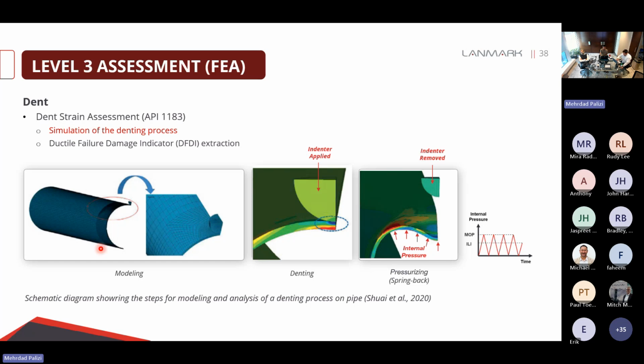So what we do here is we have the CAD geometry. We also do discretization over it. It is like a good practice to have refined mesh at the places that we have contact between our indentor and the pipe. Next step, we're going to define an indentor. We're going to define a contact between the exterior surface of the pipe and the indentor. And then we're going to apply displacement over this indentor. After we are finished with the indentation process, we're going to have the pipe pressurized. So what we do is we are applying some full pressure cycles. This is basically because in reality, because of the pressure fluctuations over the indented pipe, we're going to have some plasticity formed at some locations. And with these full pressure cycles, we're going to capture that plasticity. At the last step, we're going to just increase the pressure from 0 to the pressure at which ILI measurement was performed.